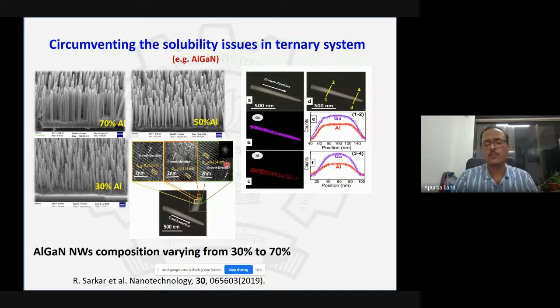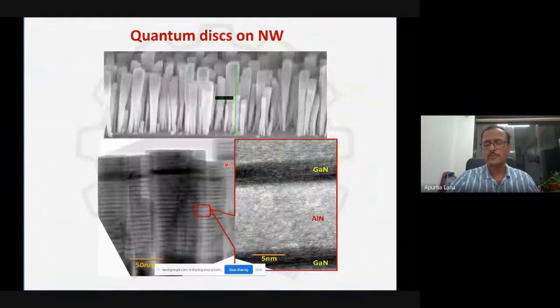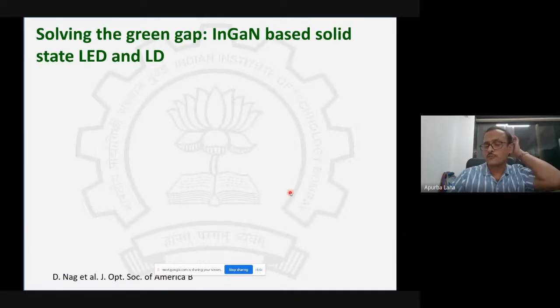You can eventually grow this nanowire on any substrate, because it's only confined within one particular region, and once you have the nucleation done, the nanowire forms and continues to grow. So that's the advantage. Once you have the nanowire based technology, you can grow whatever heterostructure you want. Now, one of the things is the quantum well that we grow for the nanowire based LEDs. Here you can see the aluminum nitride and gallium nitride superlattice, or in this case a multi-quantum well, and you can see that the interface is atomically sharp. There is no defect present whatsoever, and it is also optically quite visible. So that's the advantage once you have the best technology.